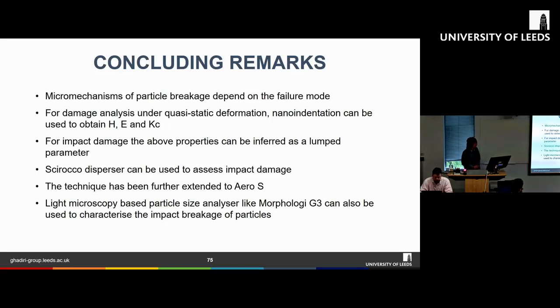The micromechanisms of particle breakage depend on the failure mode. For damage analysis under quasi-static deformation, nano-indentation can be used to obtain the hardness, the Young's modulus, and the fracture toughness of the material. For impact damage, the above properties can be inferred as lumped parameters, as I mentioned earlier in Ghadiri and Zhang's model, and we can also use commercially available devices such as Scirocco and Morphologi G3 to assess impact damage.